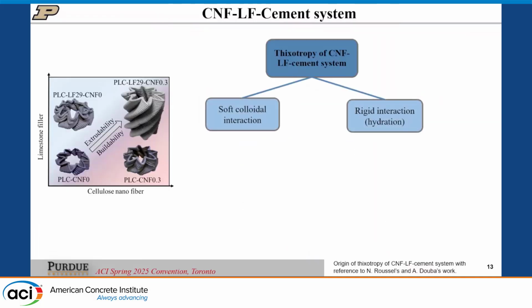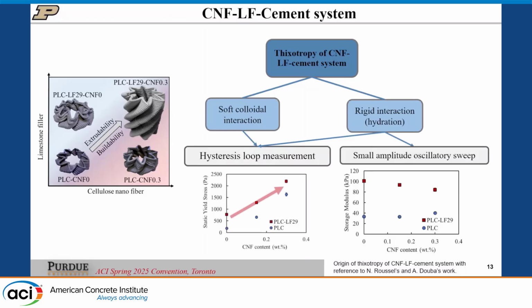Now, just trying to understand what's happening rheologically, we can simplify and look at two main properties: static yield stress and storage modulus, and the effect of CNF on them. Early on we can see static yield stress going up, but storage modulus going down. Looking at the origins of what affects these rheological properties, we see that soft colloidal interactions are leading the interactions in the system, not rigid interactions. So the effects we're seeing rheologically are more physical and less chemical.